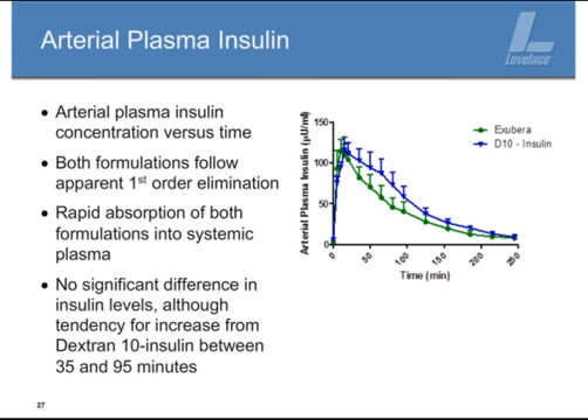The other thing that should be noted is that if you look at these graphs, the Bend Research Dextran 10 insulin material appears to have an increased insulin concentration from about 30 to 35 minutes to maybe about 90 or 100 minutes later. We evaluated the statistics on this, and while it does look like there's a trend there, that was not determined to be statistically relevant.